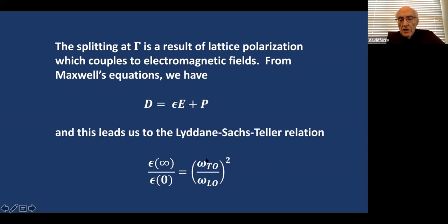And that's related to those 2 phonons. In fact, this thing is called the Lyddane-Sachs-Teller relationship. And if your phonon spectra and your dielectric functions don't match with this equation, then you've got something wrong. So this is your sanity check between your phonon frequencies and your dielectric constants that you're using.